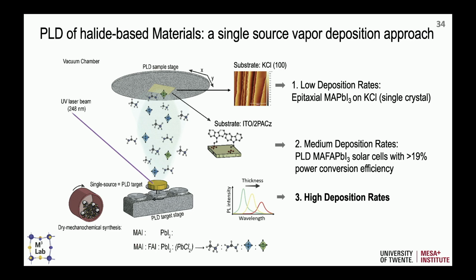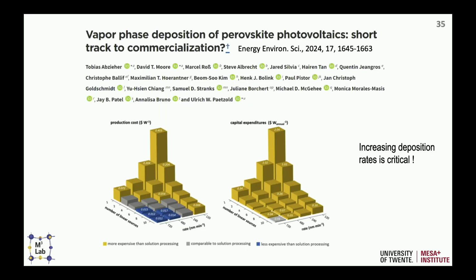Okay, so for the last part of the talk, how do we go for high deposition rates? And why do we care about high deposition rates? Juliana already showed this paper. So in this paper, it was really a question if vapor phase deposition is interesting for industry, if that will be the next step or not. And there were a lot of interviews with industry. And one of the main messages here is that if you want to do vapor deposition, we need to go for high deposition rates. If we look at co-evaporation, it could work, but it's still very slow compared to, for example, sputtering deposition.